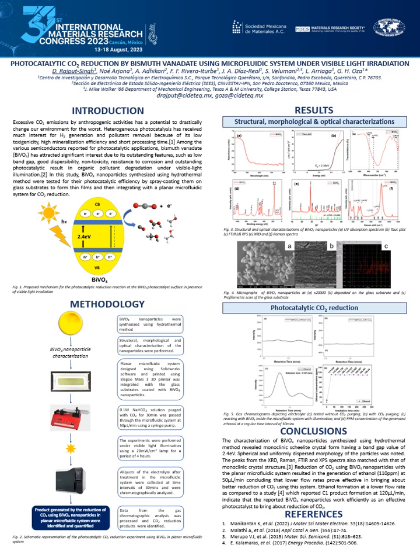Here we report the generation of ethanol at a very low flow rate of 50 microliters per minute, as compared to another report which has reported the generation of C1 compounds, and that too at a higher flow rate of 200 microliters per minute.